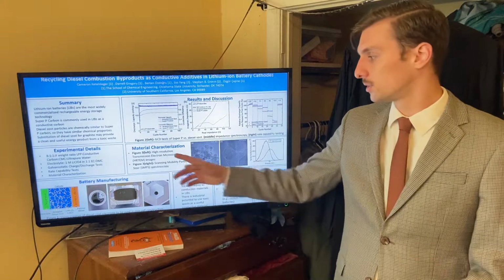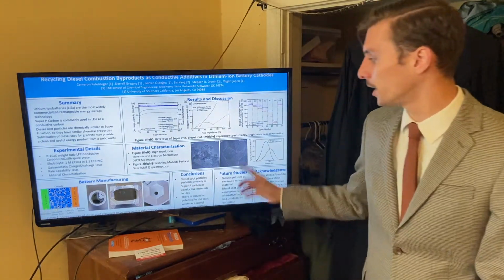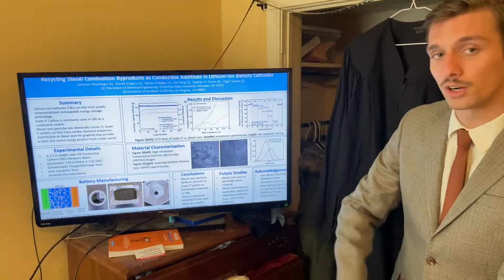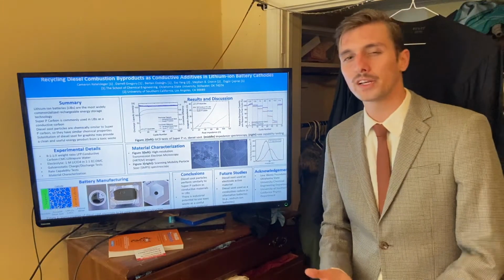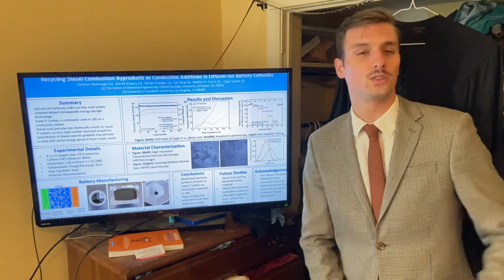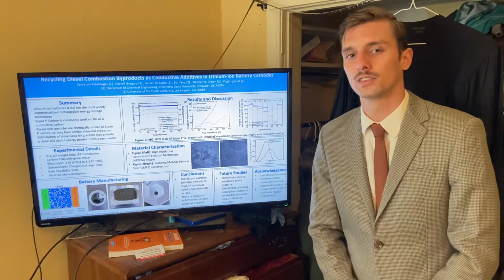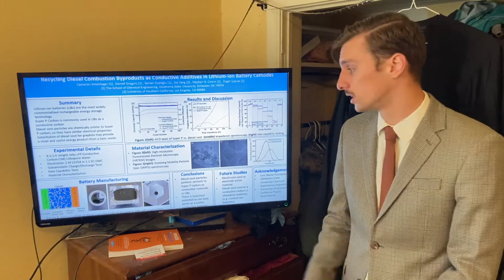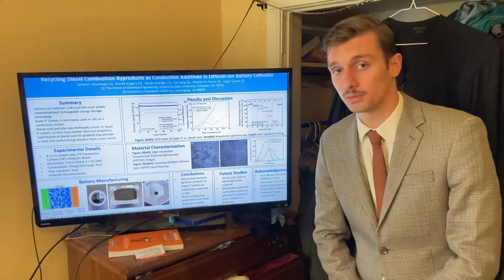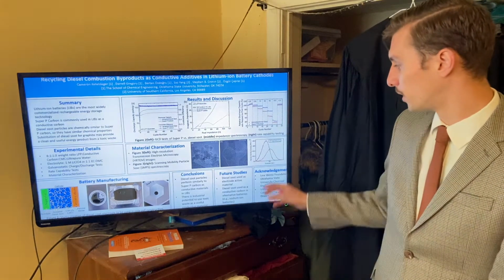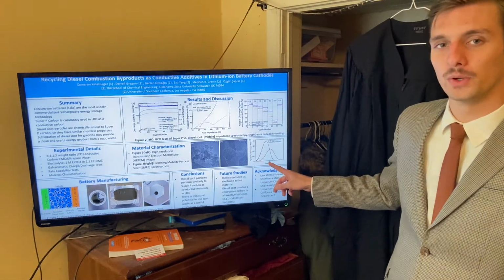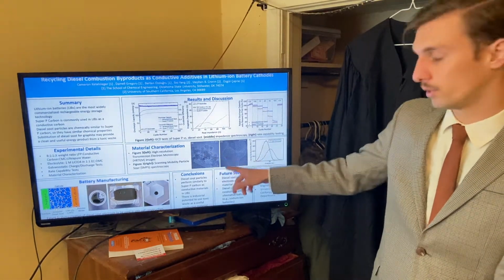Regardless, let's look at the material characterization. Right here we have high-resolution transmission electron microscopy, in which we found an average particle size range of 20 to 200 nanometers. We verified this using some scanning mobility particle sizer spectroscopy, in which we found the exact range that we were looking for in the HRTEM photos.